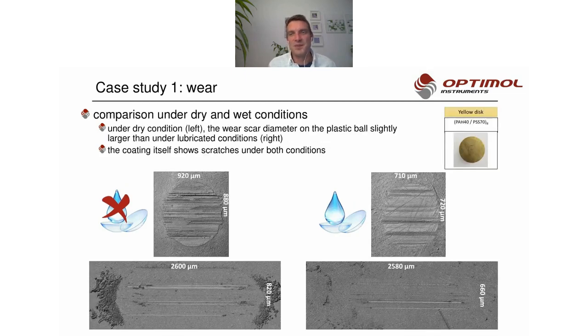For example, I would like to show you the results for another one, the yellow one. As I mentioned before, the basic task was that the coating shouldn't come off. So you need to have good bonding and no scratches on the coating. But as you can see here under dry conditions, there were some scratches already, and a lot of debris being produced during testing. On the right side, even if you add some water, the wear isn't as low as expected, and you will also end up with scratches on the coating. So this is not suitable for any applications with water on contact lenses. It was very easy to sort out those candidates.